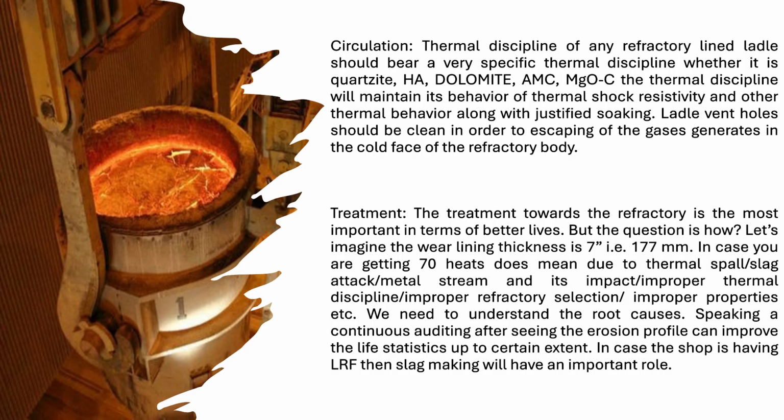refractory body. Treatment. The treatment of the refractory is the most important factor for better lives. But the question is how? Let's imagine the wear lining thickness is 7 inches, that is 177 mm. In case you are getting 70 heats, it means due to thermal spall, slag attack, or metal stream and its impact, improper thermal discipline, improper refractory selection, improper properties, etc. We need to understand the root causes.